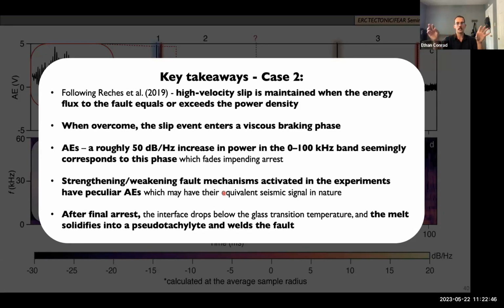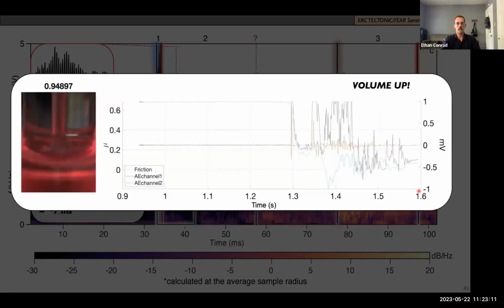The strengthening and weakening mechanisms seem to have characteristic acoustic emissions. And we think that maybe they have an equivalent signal in nature with improved instrumentation. Once we get closer and rid of the noise, maybe we can start to see these things. I don't know. And then after final arrest, the interface drops below the glass transition and the melt solidifies into a pseudotachylite and welds the fault.